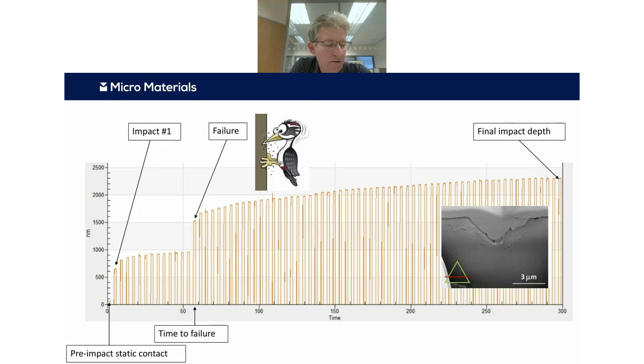Then the first impact creates a larger depth, something like 600 nanometers, because the dynamic force is much higher than the static force. And then there's this very gradually increasing probe depth over the next about 10 impacts. And then suddenly there's a big change in depth. In this case, this corresponds to material removal, so the cracking and material removal in the system.